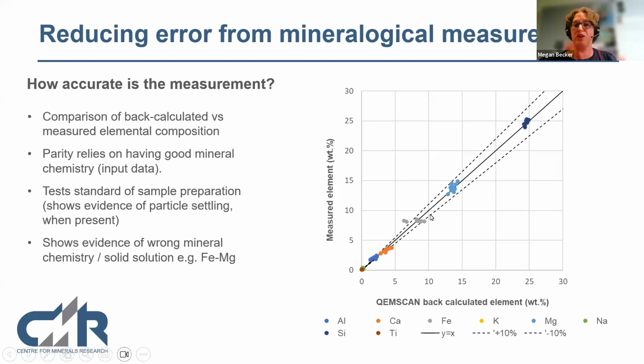If I have any issues with sample prep, I might see something like iron. If I saw the gray dots belonging to iron plotting out here, so I'm overestimating the iron, then I know that I potentially have had settling in my samples. Sometimes we juggle things like iron and magnesium. If one's high and the other's low, we know that because many silicate minerals can take different ratios of those elements into the same mineral. We just have to tweak the compositions that we're using to back calculate this number, and then we can pull it to the line. So that's one method, but that just gives me confidence that I've calculated the right compositions.